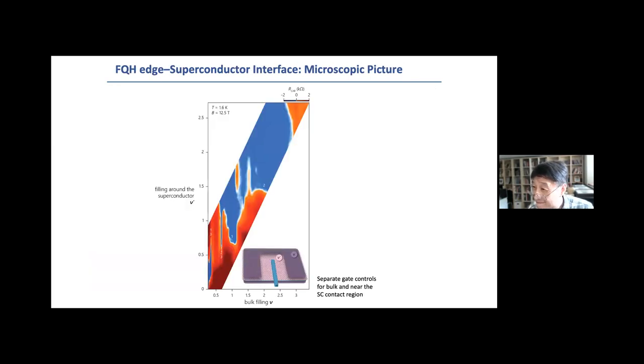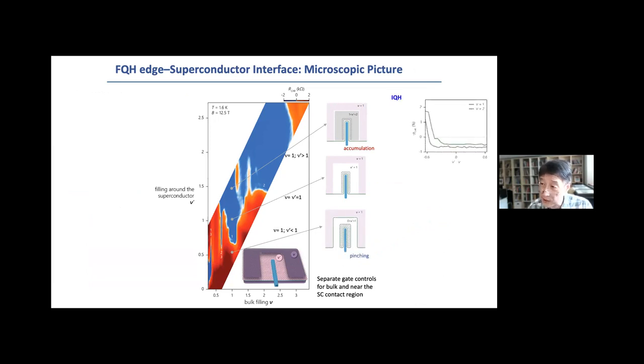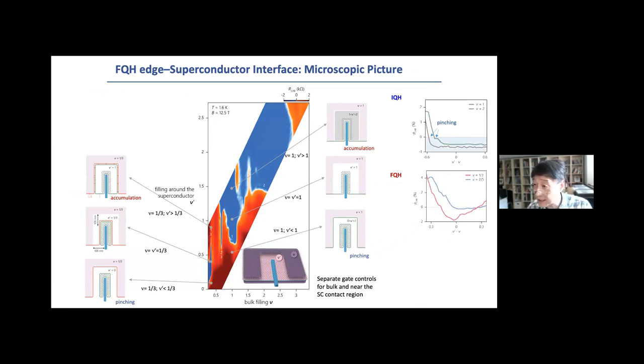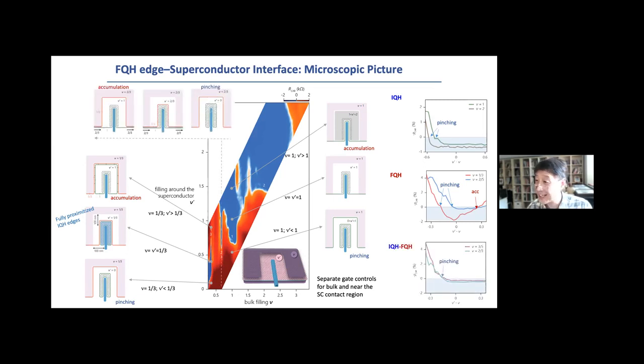I know that Jerry is now pushing me, so let me not go into the details, but all of these things can also be carefully discussed by changing the chemical potential near this contact area. We can just take a look. Indeed, 1/3 and 2/5 go through a rather different process from all other integers or even other fractions at higher filling fractions. This also strongly indicates that we are seeing the fractional Car process is rather different from the integer Car process. And that basically indirectly supports the idea of the formation of the parafermion, in my opinion.